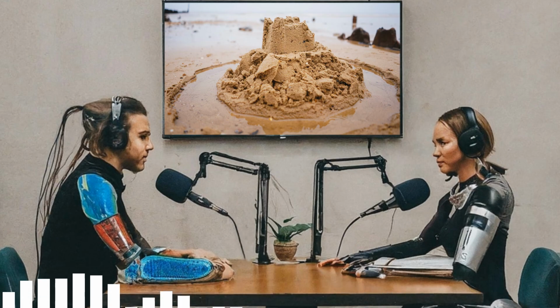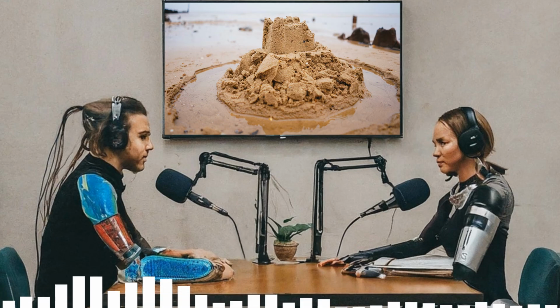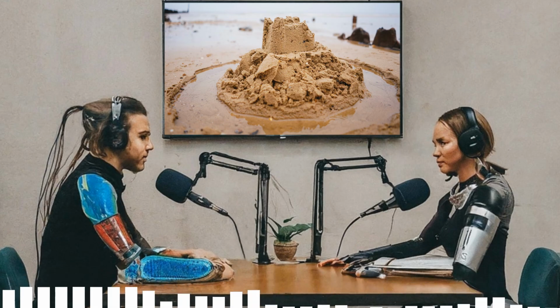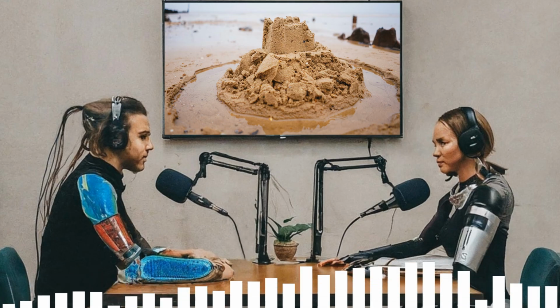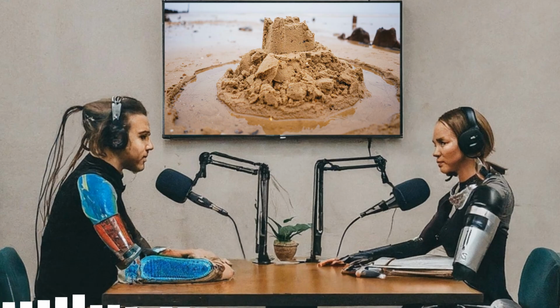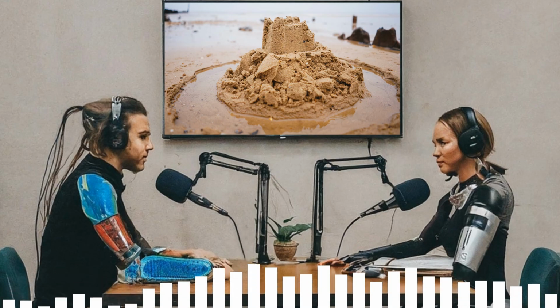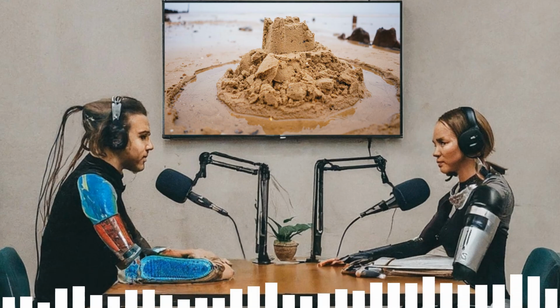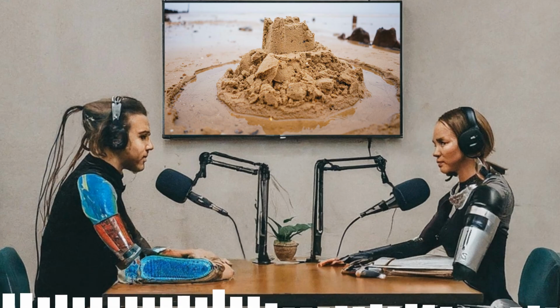And the technique they describe is pretty clever, too. You mold the parts underwater so they're full of trapped air between the grains. Then, and this is cool, you use a syringe to actually suck out some of that trapped air. This reduces the volume of the fluid, the air in this case, from maybe 40% down to 10%. And just like reducing water content above water, reducing the air content underwater makes it stronger. The paper concludes this makes it possible to build even more spectacular sandcastles underwater than normal ones.